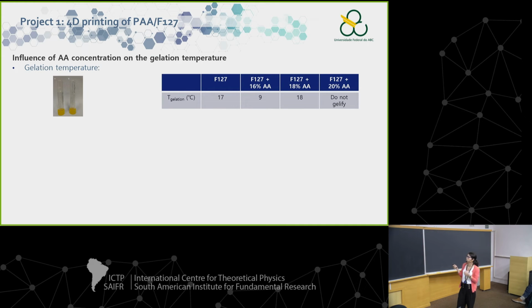For Pluronic, it is 17 degrees C. For 16% of acrylic acid, it is 9 degrees C. Then it increases again, and in the case of 20% of acrylic acid, it doesn't gellify, so it is not adequate for 3D printing, otherwise it will drop from the syringe.